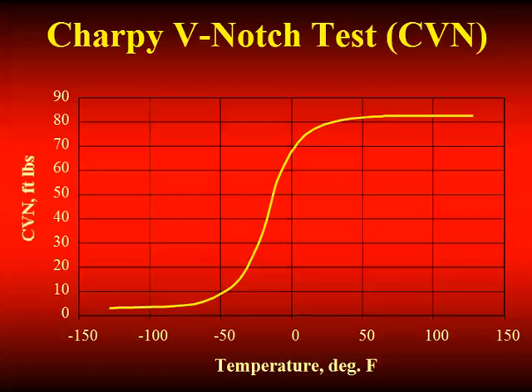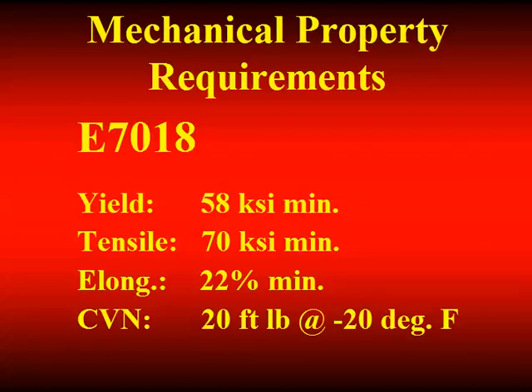Of course, conversely, the higher the transition temperature, the lower the toughness of the material at higher temperatures. We've specified toughness on bridge steels and bridge weldments for probably 30 years now, going on 40 years. In the steel business, we've not typically specified toughness. Since the 80s, we've had toughness on the core regions of jumbo sections loaded in tension. They're subject to welding. In the post-Northridge era, we have toughness requirements on the weld metal, and that gets into the CVN numbers. Again, that's buried in the E7018 designation of this particular electrode, and that's required to have 20 foot-pounds at minus 20 degrees.